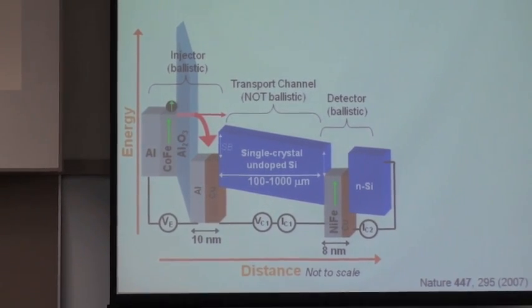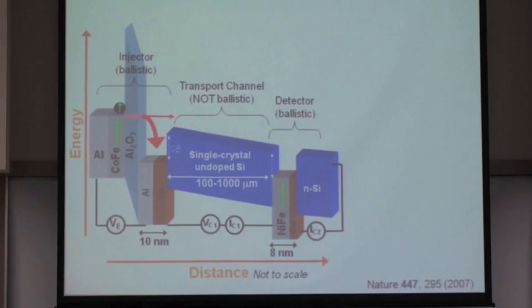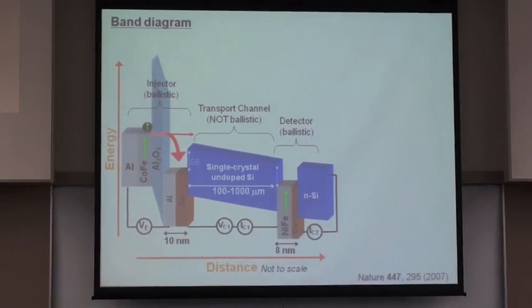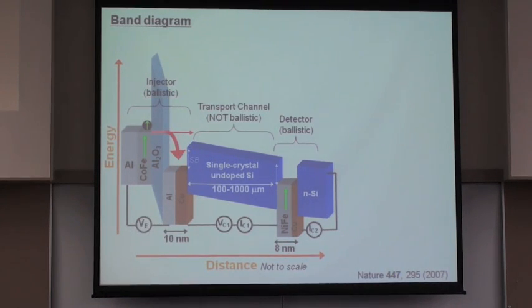Now, what happens is that we're injecting these hot electrons very far above the conduction band edge. Once they cross over the interface into the semiconductor, they subsequently have to relax down to the conduction band edge by a cascade of phonon emission. But this occurs over a very short length scale, typically 10 or so nanometers. So what this means then is that throughout most of the transport distance, which is typically several hundreds of microns, the transport occurs at the conduction band edge and is subject not only to drift in the presence of an internal electric field provided by a voltage drop between the anode of our tunnel junction injector and the other side where we detect, but also it's subject to the random motion of diffusion. I'll show you what the consequences of that are in a moment.